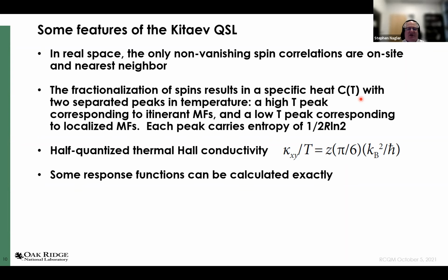If I put in a magnetic field and sort of gap the bulk, which in this case, of course, is a two-dimensional surface, it turns out that I don't gap the Majorana fermion spectrum around the edges. And this gives me something that's somewhat analogous to what you see in topological insulators. I have a half quantized thermal Hall conductivity in units of, here, this number Z is half odd integer, or in units of a half. So this is quantized in units of heat carried by half an electron.